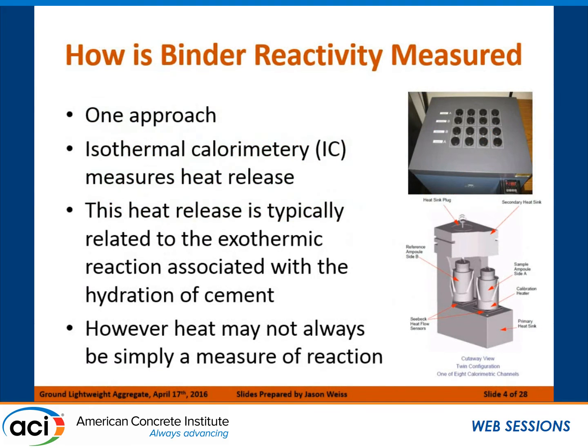One of the things I want to start off with is how we're measuring the reactivity of various binders. One approach, which is used a lot because it's a very easy approach to use, is isothermal calorimetry. The idea here is that we measure the heat that's released during hydration. We have a rule of thumb with Portland cement that the heat released through the exothermic reaction is related to the hydration of cement.